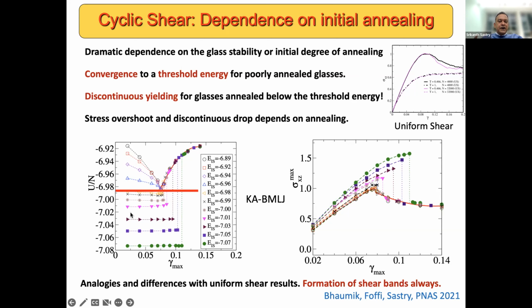But if one looks at deeper energy minima or better annealed glasses, the behavior changes completely. Below this red line on this energy versus strain amplitude plot, there isn't much happening to the energies of my glasses till some strain amplitude at which I exhibit a discontinuous change. And this discontinuous change becomes bigger and bigger as I go to lower energy or better annealed glasses. The same kind of behavior is exhibited by the stress-strain curves, where the stress overshoot as well as the drop to the yielded state in the stress increase with an increase in the annealing of the glasses. And these drops, as I'll come to in a little bit, are always accompanied, in the case of cyclic shear, with the formation of shear bands.